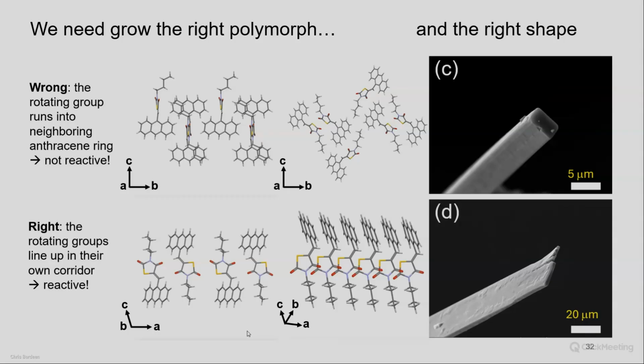Now there's one other subtlety that I didn't mention, which is that polymorphism also controls crystal habit. So the ability to grow long, thin microwires, which are ideal to observe this motion, depends on the polymorph as well. If you have the wrong polymorph, it may be reactive, but if it grows in a big block that's thick along all three dimensions, you won't see any mechanical motion. You'll still see the photochemistry, but you won't see the photomechanical response because it's too difficult to deform that brick of crystal. So polymorphism is super important, both for controlling reactivity and for controlling the habit of the crystal, so that reactivity can manifest as a mechanical response as well. So, a very long answer to your question. The short answer is yes, totally important. And you want to look for a polymorph that's less dense, or at least opens up some space next to the reactive unit of your molecule.